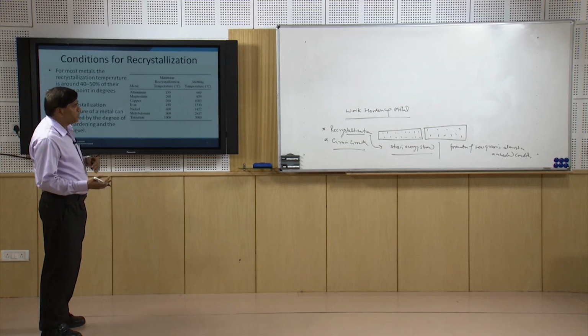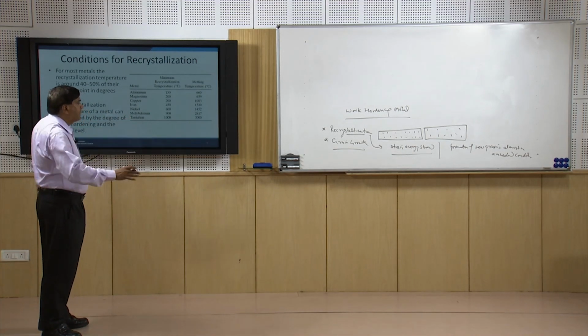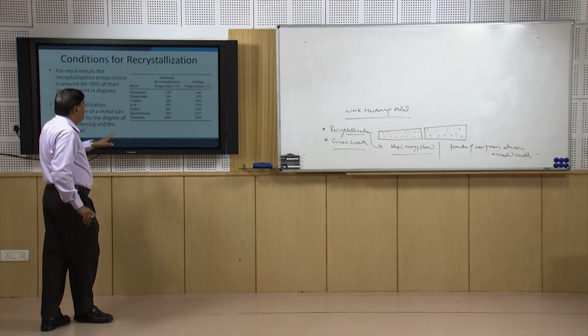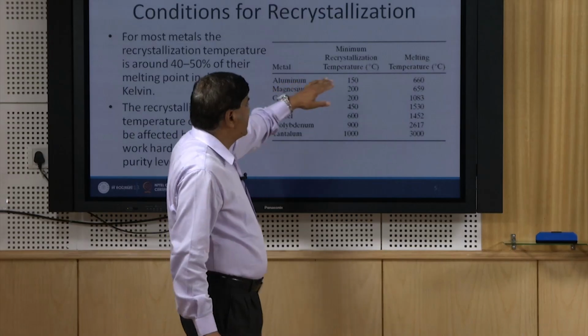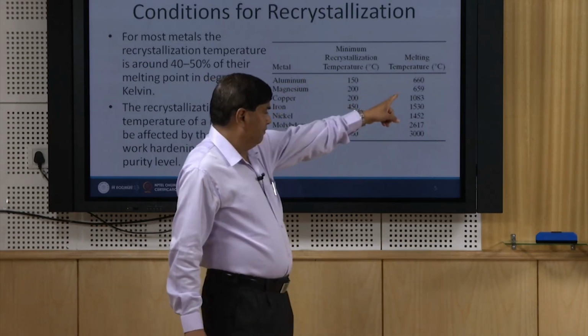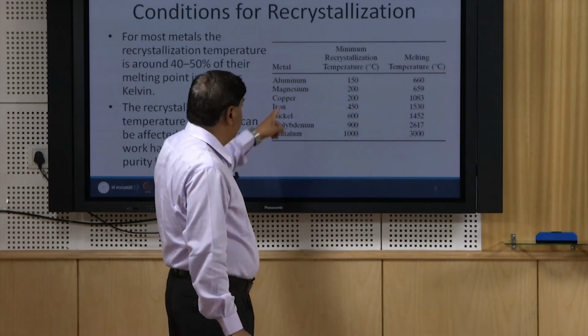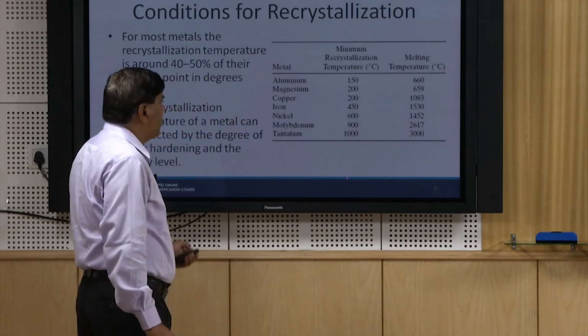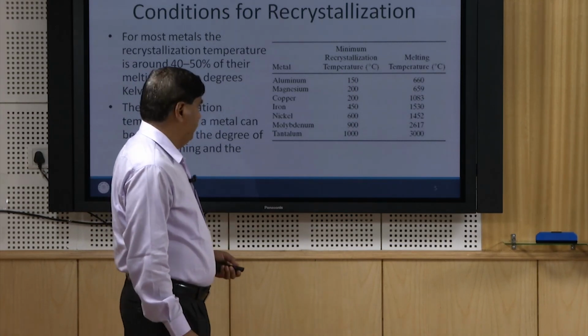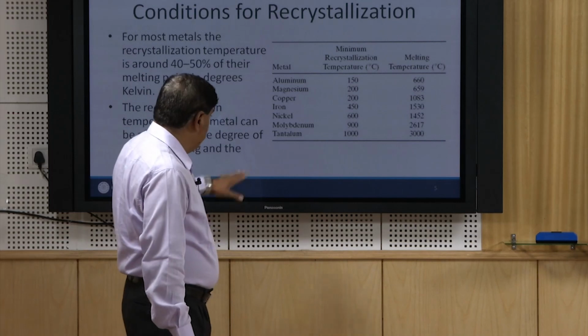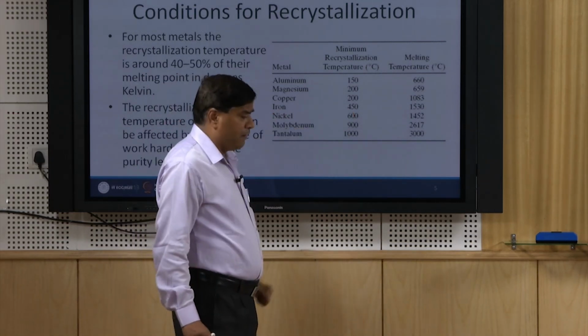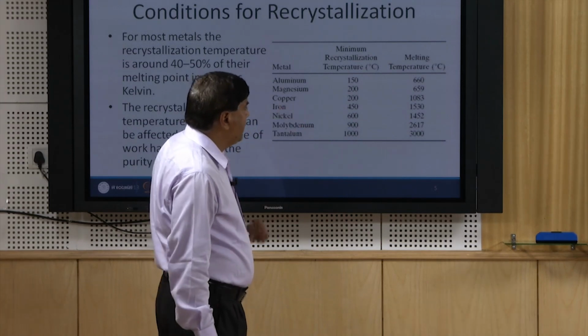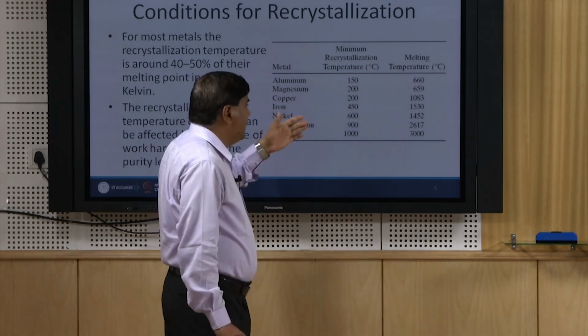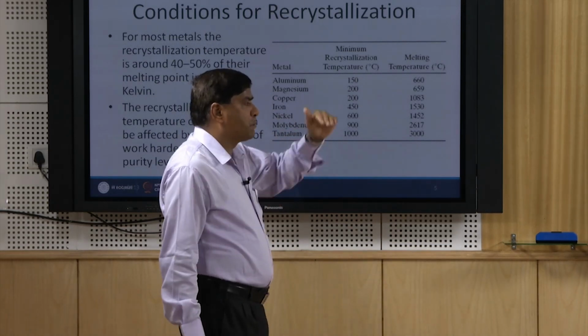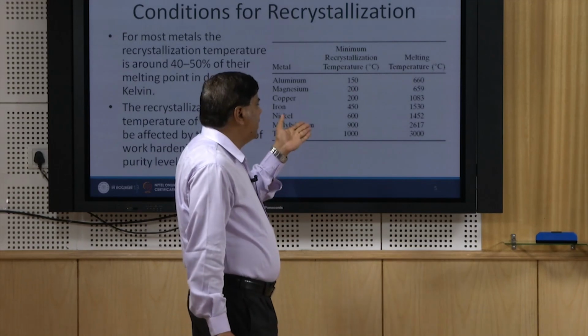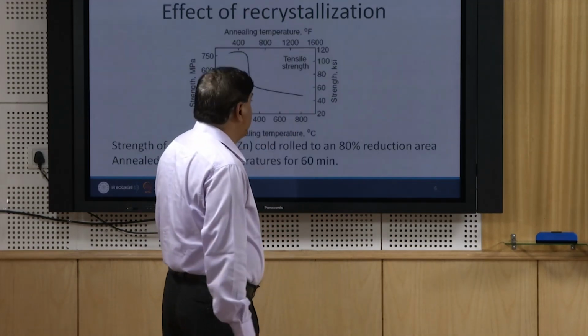So, the different metal systems show the recrystallization tendency at different temperatures. With respect to the metal systems, what we can see here, aluminum recrystallizes above 150 degree centigrade while its melting point is 660 degree centigrade. Similarly, magnesium recrystallizes above 200 degree centigrade while its melting point is 659. Similarly, iron recrystallizes above 450 degree centigrade while its melting point is 1530 degree centigrade. So, likewise, each metal will be recrystallizing as soon as exposure above a particular temperature is given, and this is found to be significantly lower than its melting point.